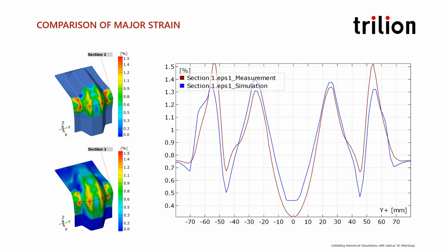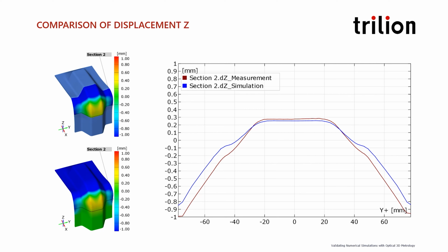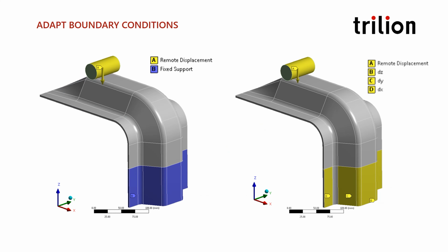Keeping the section line and just updating the inspection to major strain, the ARAMIS reality data in red shows those same large differences. Then again, across displacement in the z direction, you can see the outer edges of the bumper are simply displacing more than the simulation had predicted. In consideration of our test setup, our fixture may not be the most fixed at the base. If the condition was loosened a bit in the simulation, it may account for the extra displacement.